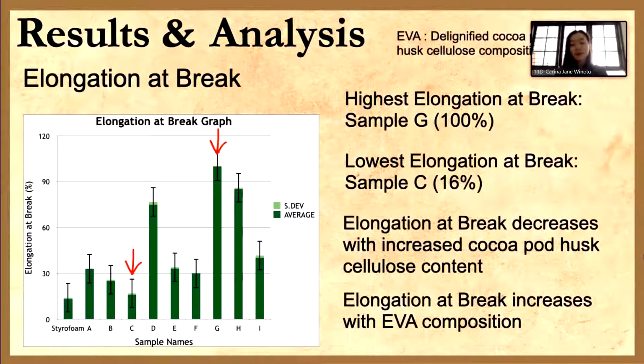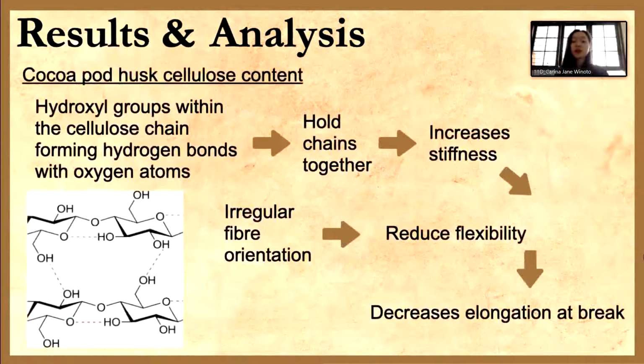Therefore, with sample G having the highest elongation at break value, it can be said that sample G has the tendency to deform up to 100% of its original length, while sample C tends to fracture at an increase of 16%. Looking back at the graph, it can be seen that increased cocoa pod husk cellulose content decreases elongation at break values, while EVA composition increases it. That again can be explained using the same explanation as before.